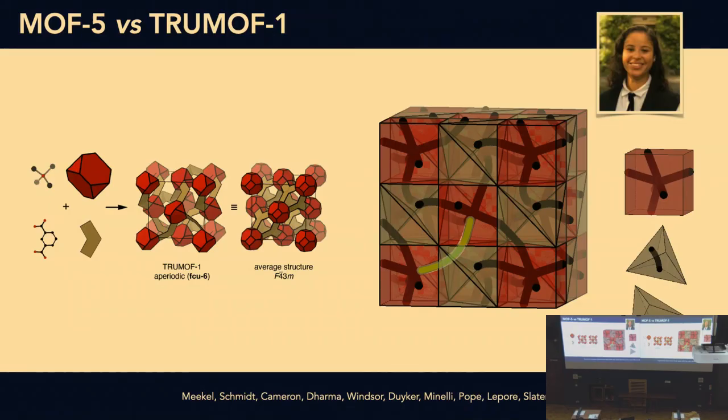And when you grow the crystals of this material, what you find is some diffuse scattering. I'll show you in a moment. Some Bragg reflections. And when you solve the structure from the Bragg reflections, you get a very high symmetry structure like this, with clusters on a face-centered cubic lattice. And the linkers, we know chemically we've put them in as cis, but it looks as though we've got sort of triplets of them, for example. And they've all got partial occupancies.